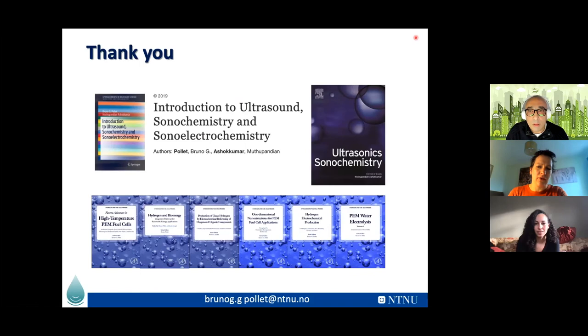Yes, yes. One of the papers, 2005, I think, we looked at a deep eutectic solvent and RTIL. So we actually demonstrated we could do the sonochemistry and sono electrochemistry in those solvents. Yes. Absolutely. The thing which is very interesting is that what we showed is that if you have prolonged sonication, you are also affecting the deep eutectic solvent.